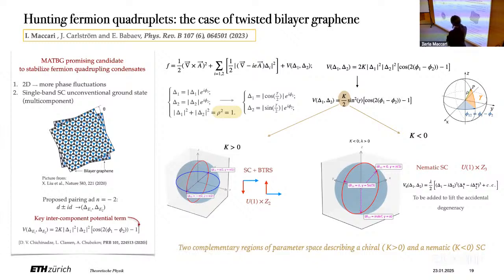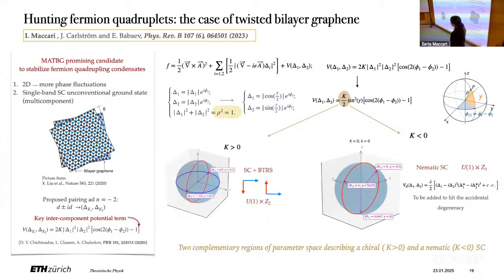So this quadratic term comes, of course, from the symmetry of this order parameter. But yes, in principle, we are now investigating this case. For the nematic case, it's a bit more difficult to stabilize. What we are finding, as a spoiler, is that there is no splitting. So it's relevant. I guess that the story can be extended to more than two components. Yeah, definitely, it just gets more complicated.